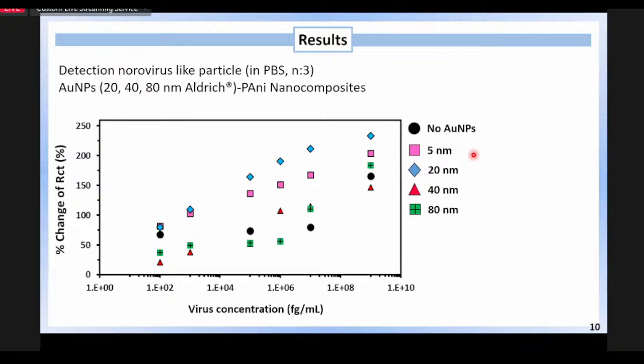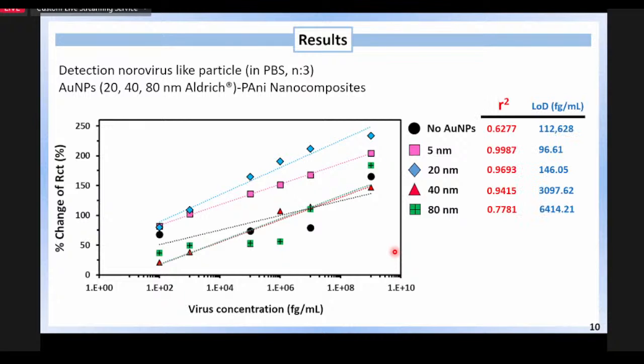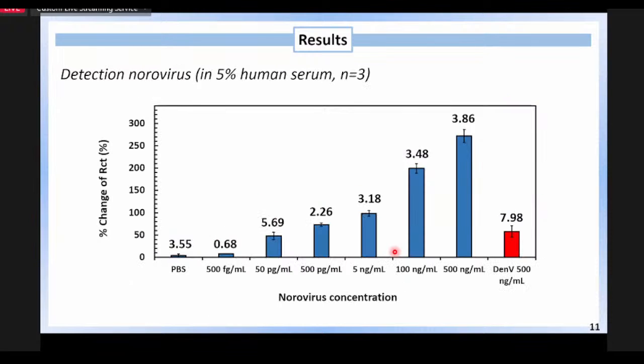So yeah, this is the trend of the calibration curve when we are increasing the concentration of the virus and evaluate the dose-dependent response from the EIS. And this is the regression curve. And then what we could see here is 5 nanometer gives a much lower limit of detection compared to the other nanocomposite. Here, after getting the good result from the previous slide, I'm